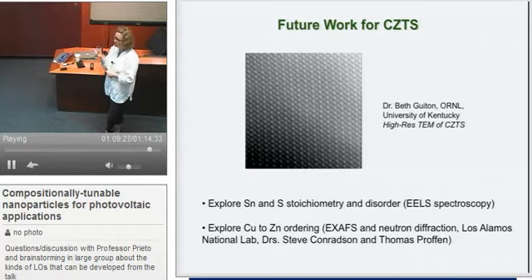And with neutron diffraction, copper and zinc are very different. So there's a theory paper that said that that cartoon I showed you with the 2 coppers, 2 zincs, and then you flip them, if you could get them ordered, the efficiency would be higher. We are not ordering it. I mean, it's totally random in terms of the copper and the zinc. And more importantly, by XAFS now we know that the local bonding is also very variable.